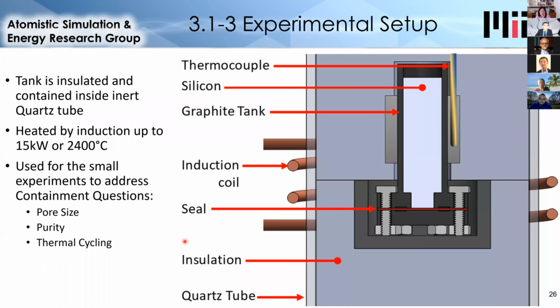So for the first set of experiments, I designed a small system which consists of a tank that's about 4 inches tall, made of graphite, shown on the left, filled with silicon and heated by an induction furnace, which electromagnetically heats the system contained within insulation. This is a small, relatively simple experiment for determining the effect of pore size, silicon purity, and thermal cycling.